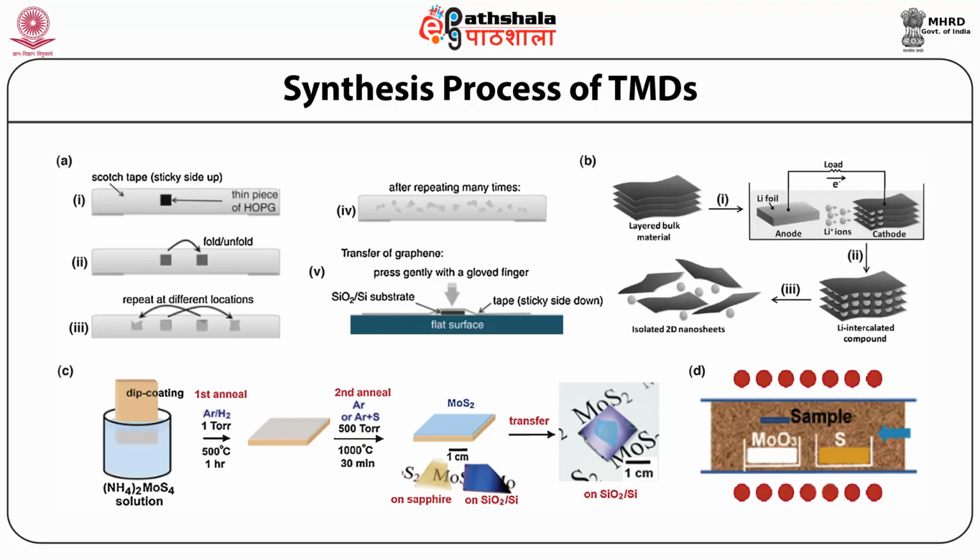The nanosheets are dispersed by sonication in an aqueous solution of the surfactant sodium cholate, which coats the sheets, preventing their reaggregation. These direct sonication techniques rely on the solvent or surfactant to overcome the cohesive energy between neighboring layers, which means the solvent must be chosen to have a surface energy comparable to that of the material.